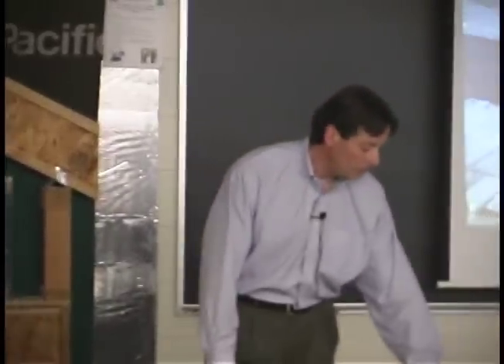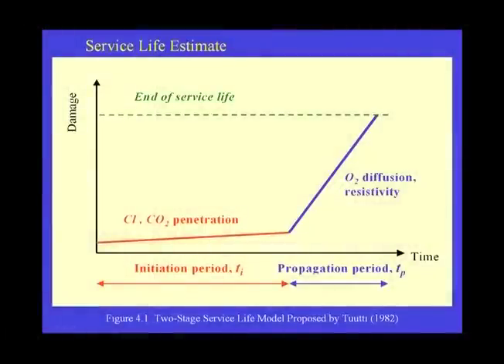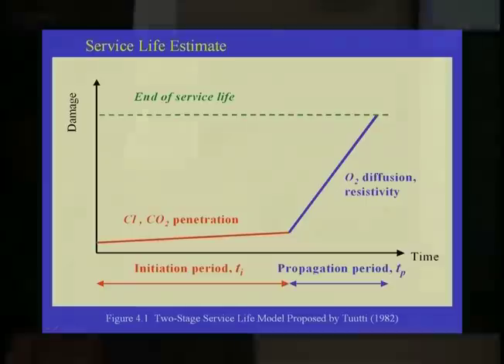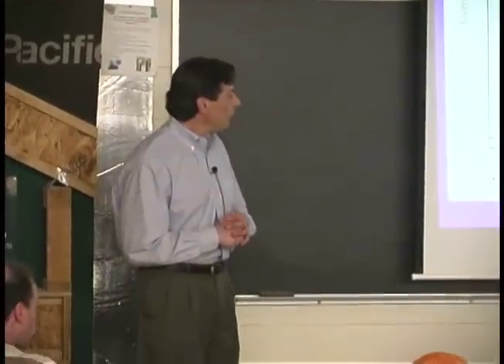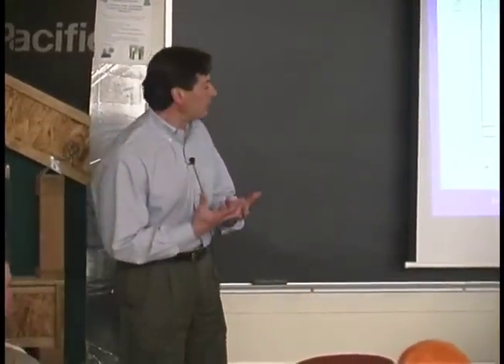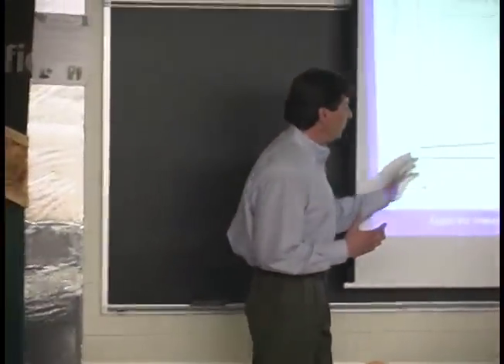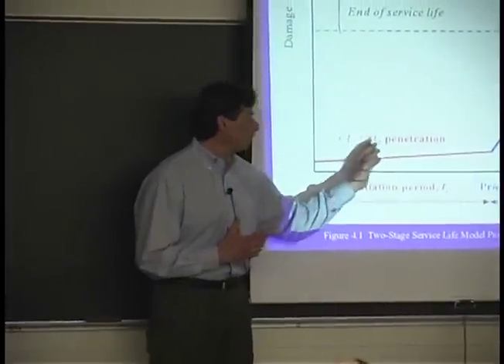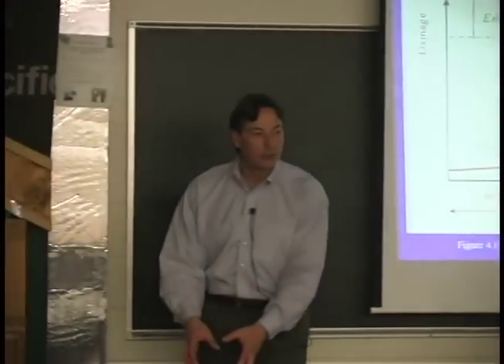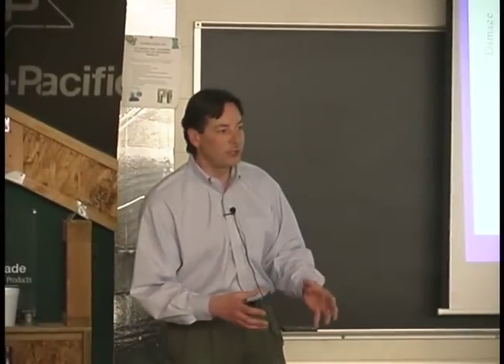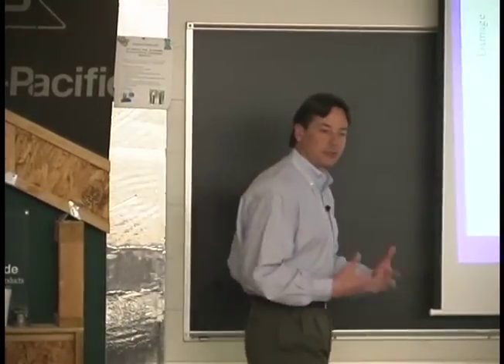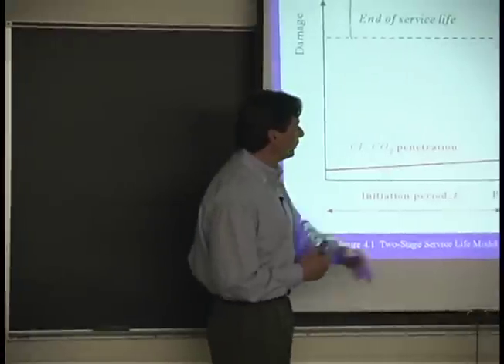But what does service life mean on something like a parking deck or a bridge? This is a famous way of depicting it from Professor Tuutti back in '82. Concrete acts as a sponge. That's this initiation period here, where it's allowing chlorides and carbonation to actually penetrate and get into the concrete. There's no corrosion happening at that point in time. It takes a certain amount of electrolyte in the concrete to start corrosion.